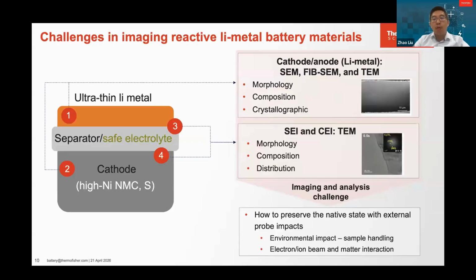Because most of the materials are very reactive, they are majorly impacted by two different probes. One is what we call the environmental probe, related to the moisture or oxygen in the environment. Another is the electron or ion beam used during imaging or sample preparation, which reacts with the materials and can potentially damage the sample. So the question, or the challenge, is how we preserve the sample in its native state when external probes exist.